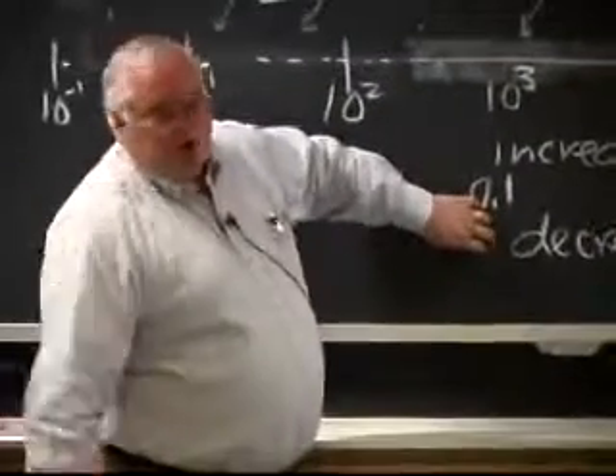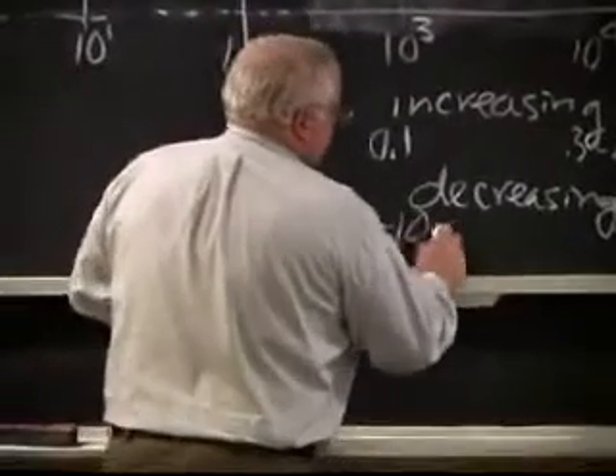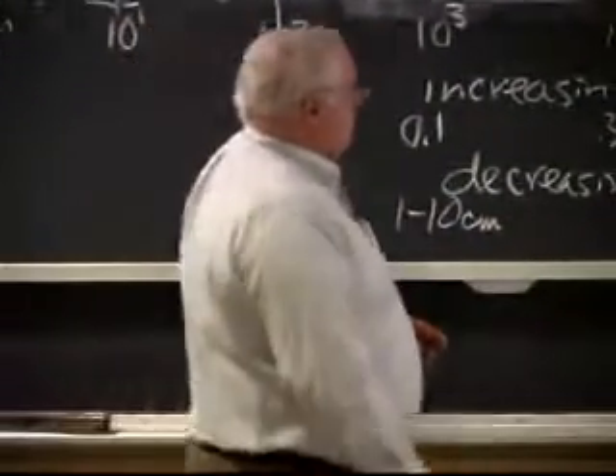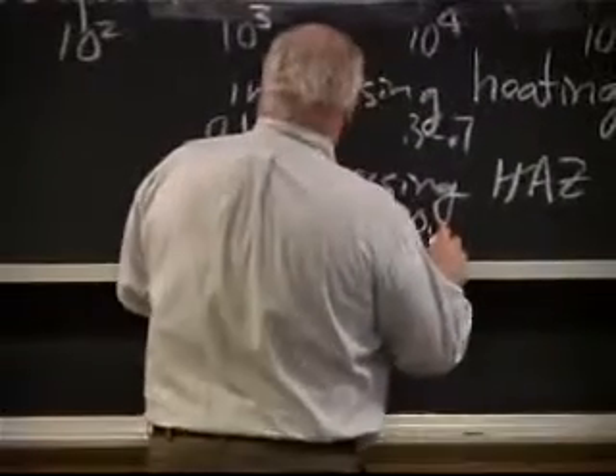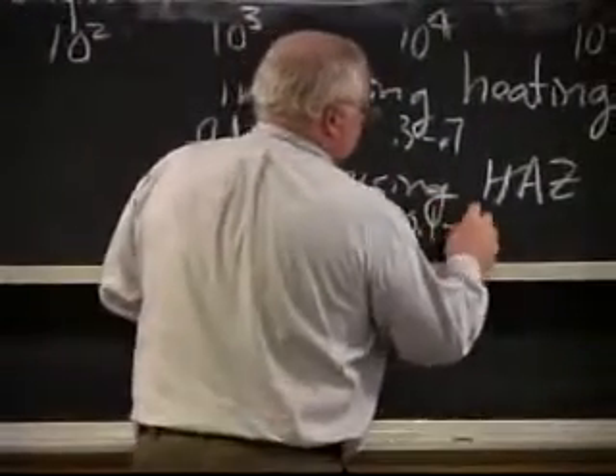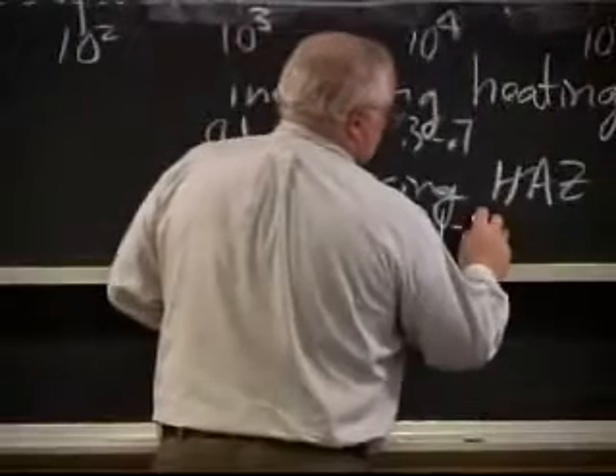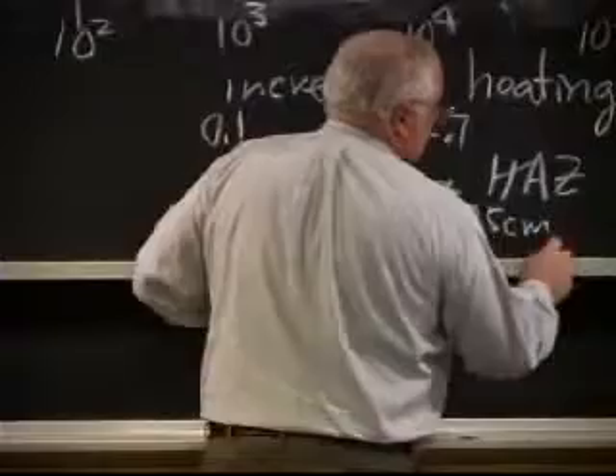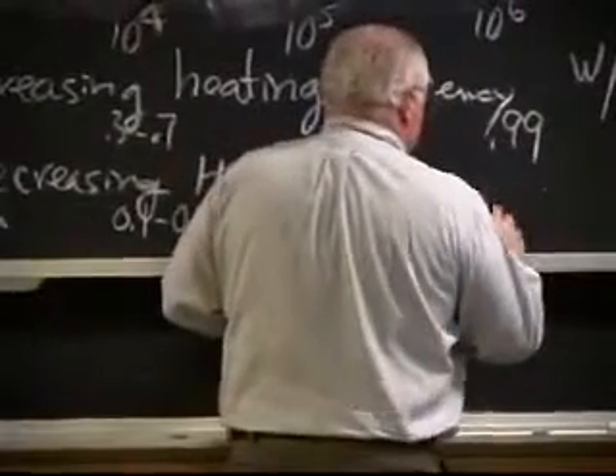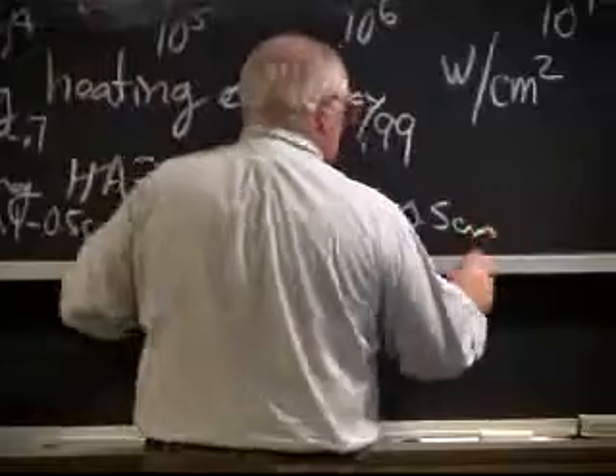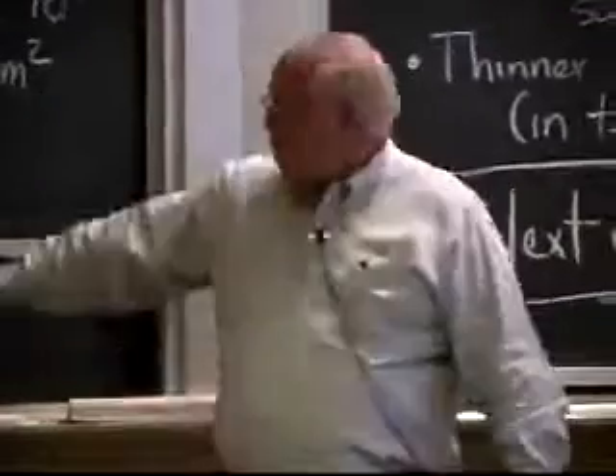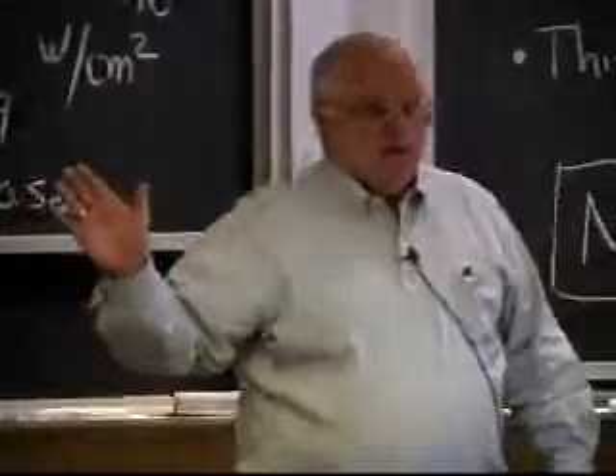I think when I handed around that piece of HY80, you could see a heat affected zone several millimeters in size. It turns out if you are putting in a lot of heat and wasting the heat and some of it's diffusing away, you're going to have a big heat affected zone. So the heat affected zones over here can be on the order of 1 to 10 centimeters in size in steel or something like that. Here they'll be on the order of a tenth of a centimeter to maybe a half a centimeter in size. And over here, it turns out there'll be a tenth to a half a centimeter in size. They don't get any smaller once I go above 10 to the fourth. Anybody know why that is?